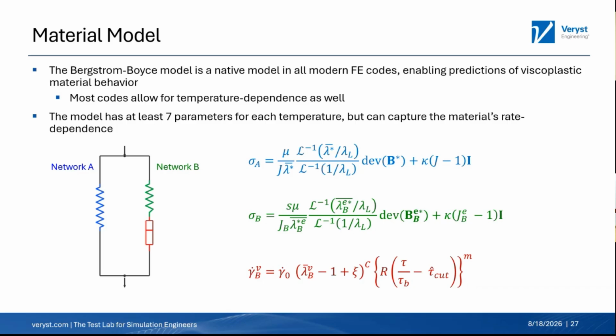So that gives us an elastic response. The green equation there is the stress in network B, which is the stress in that hyperelastic spring. It's the same thing as A, but we put a parameter S in front of that shear modulus mu, and that gives us a way to change the relative stiffness between these two networks. The third one is the shear flow rate of that dash pot given there in red. This is sometimes called a Bergstrom flow element.